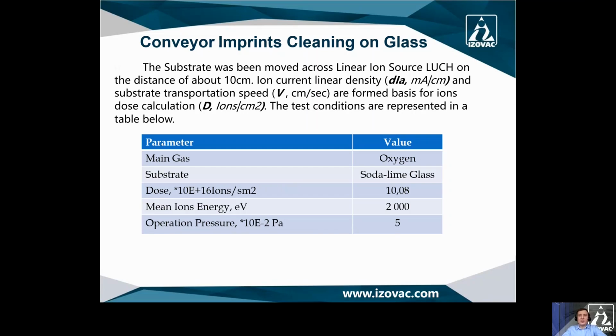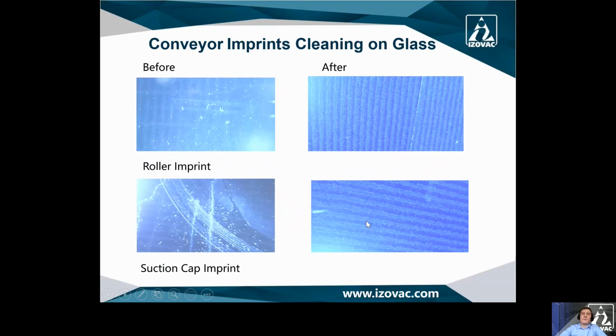The test conditions are represented in a table. Main gas is oxygen. Soda lime was used as a substrate. Dose is indicated here, as well as mean ion energy and operation pressure. What is the result? Take a look at the pictures before and after. You can see after the treatment the glass appears transparent and there are no imprints on the surface.